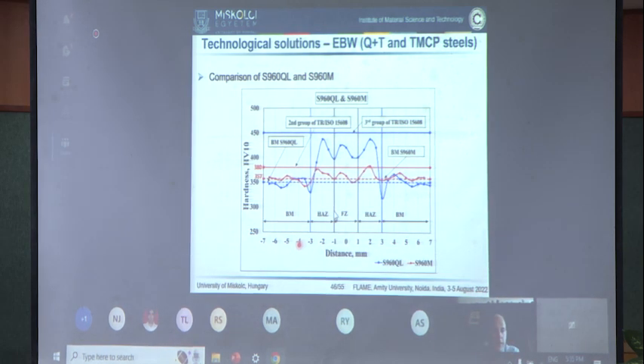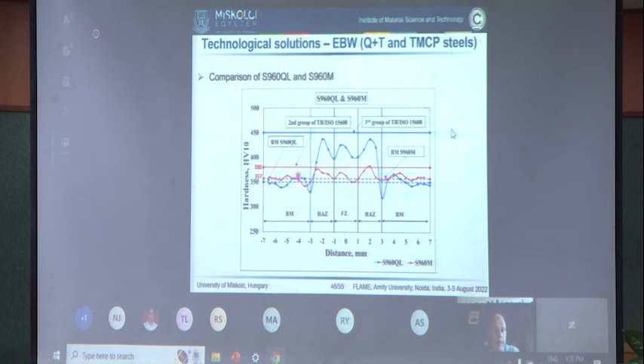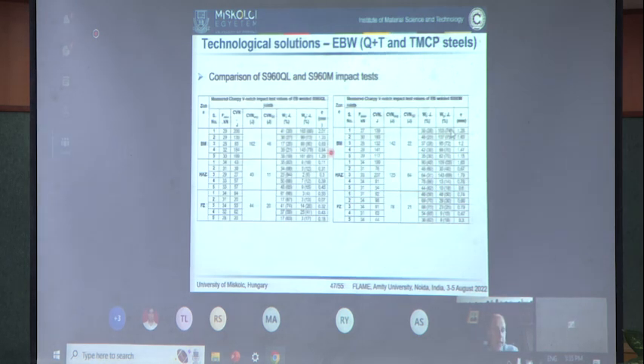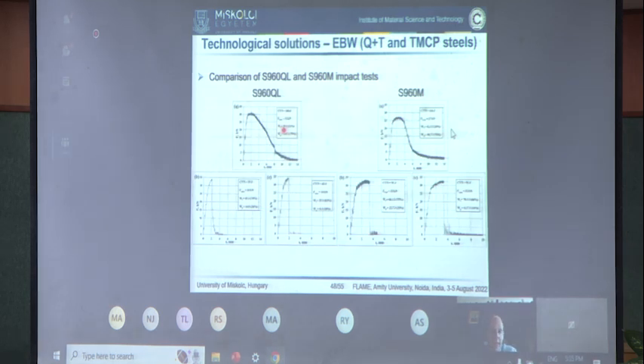conventional arc welding technologies. If we compare the characteristics of the 960 grades in quenched and tempered and TMCP condition, we can say that TMCP high-strength steels are very ideal in terms of the hardness. There is no significant hardening in the weld and in the heat-affected zone compared to quenched and tempered steels. And if we analyze the impact energy values, we can also see that by the thermomechanical rolling, in most cases, the toughness characteristics of the welded joints are better compared to quenched and tempered steel.